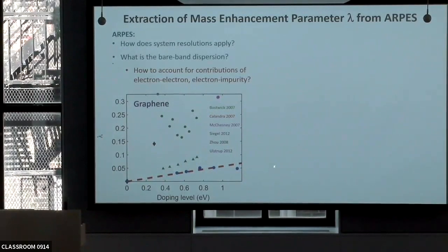The blue data for the graphene case were obtained by Lanzara's group in two ways. One is taking into account deviation from linearity of the band that is used to describe the Dirac point. At the same time, the graphene is not grown on silicon carbide, which is usually the case for most of this work in order to do photoemission, but grown on copper. So having a metal underneath, where you have an electron gas that would shield correlation effects, that is the claim. In this way, you can get something that matches what DFT tells you. But you can see the challenge in this case. And this is a case where correlations are not particularly important.